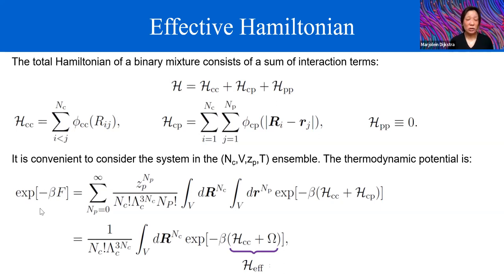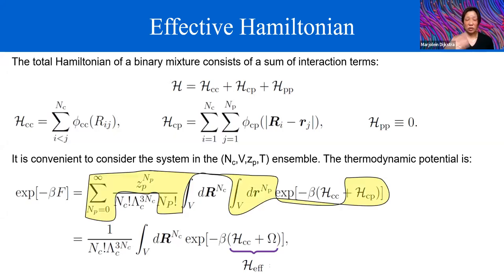One can write down the partition function. It is convenient to treat the colloid particles in the canonical ensemble while you treat the polymers in the grand canonical ensemble. So the partition function is a sum over the number of polymers, and then a trace over the coordinates of the colloids, a trace over the coordinates of the polymers, weighted with the corresponding Boltzmann weights. If you then trace out all the degrees of freedom of the polymers, so that's basically this yellow beast, you end up with just a trace over the colloid degrees of freedom with a Boltzmann weight that corresponds to an effective Hamiltonian. This effective Hamiltonian consists of the pair interactions between the colloidal particles, this hard-sphere-like potential, plus an omega, and this omega is basically the grand potential of the polymers in the external field of the colloids in a fixed configuration.